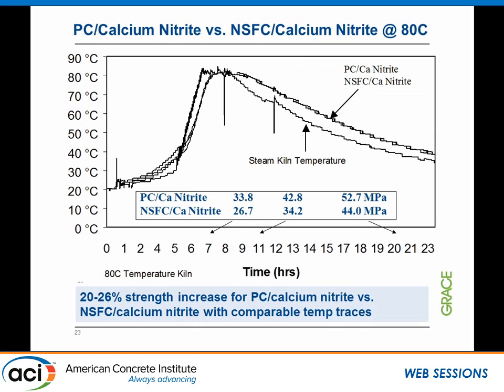And so we come back to the lab and say, okay, is this really real that we're getting so much strength increase in the field? We did a test in here with a steam cure at 80 degrees Celsius. In terms of the calorimetry curve, the heat curve, you're seeing the heat profile is about the same. But at the different times, you do really realize the differences between the strength of the polycarboxylate and the calcium nitrite. 34 megapascal in here versus 27, and all the way at about 21 hours, 53 versus 44.